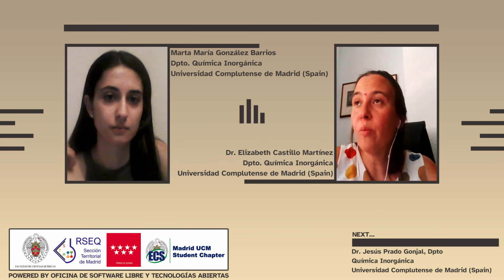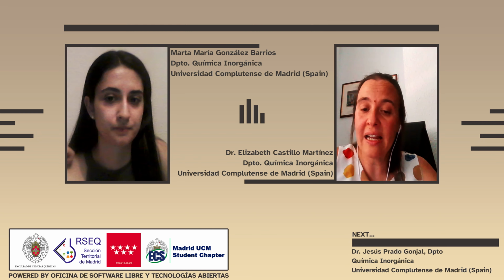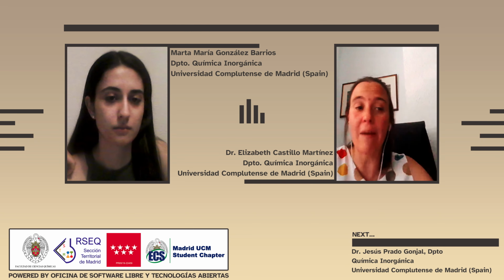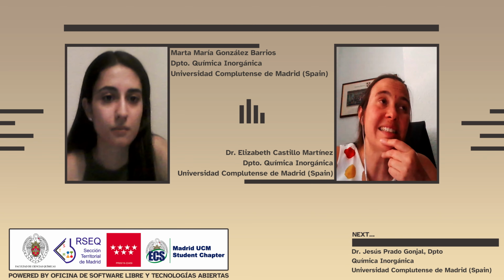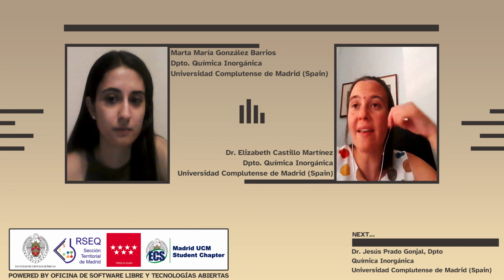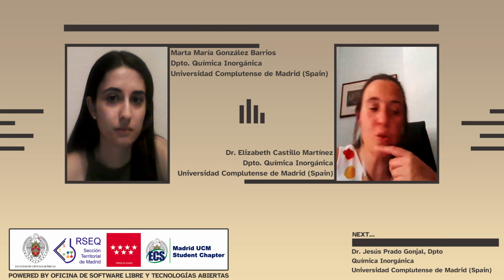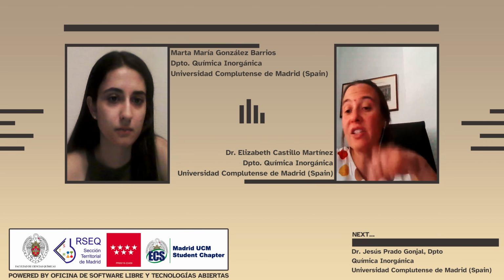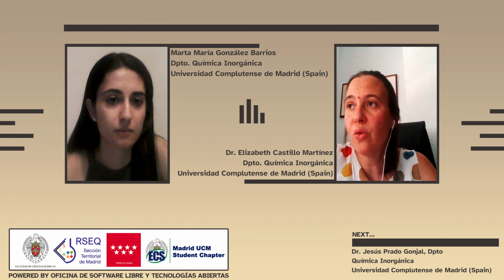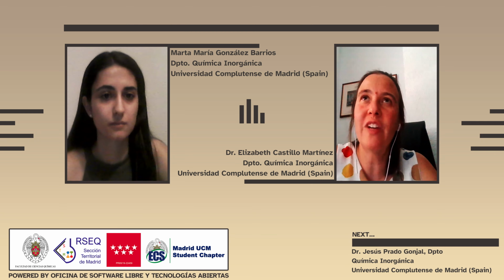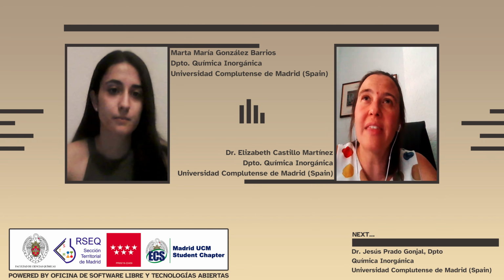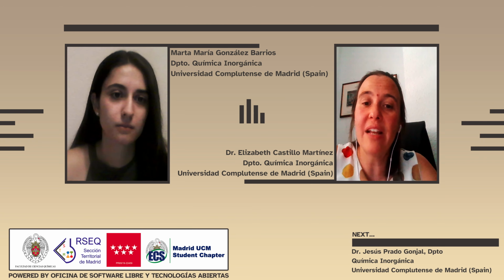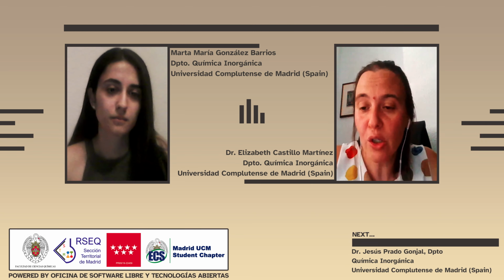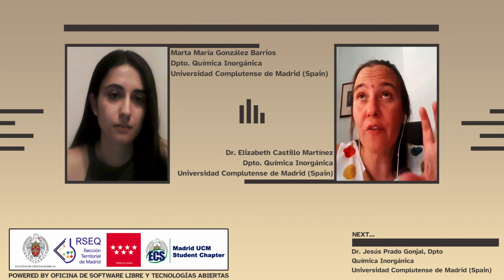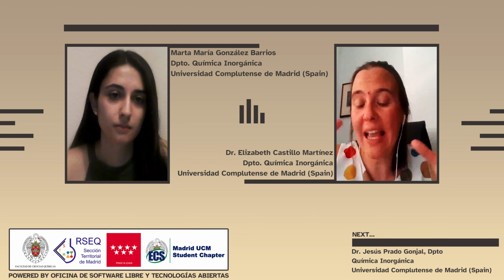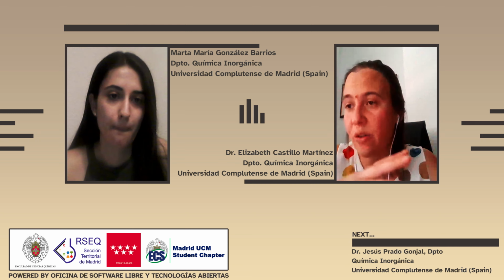So the preferred choice will be to use, as I mentioned at the beginning, a metal electrode material in the middle of a plateau region, or just to use an external reference, like maybe a silver or a platinum wire, but careful with platinum as it can promote decomposition of the electrolyte, so maybe a silver wire and some ferrocene. But this is not very commonly done. I would think once you characterize your material in a 3-electrode cell, it is more common to then try to build a cell completely free of sodium or potassium, a 2-electrode cell against another cathode, if you're studying another material, against another cathode already well established.